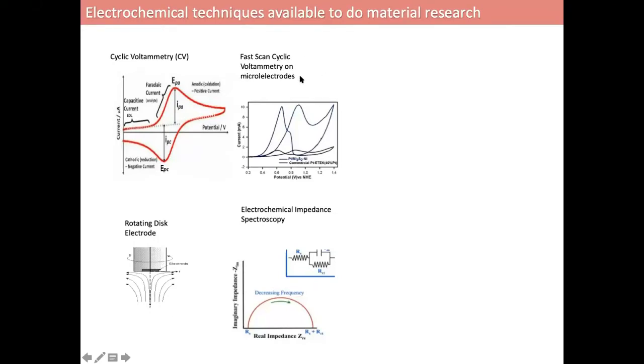It has to be done in a microelectrode. We're going to talk about microelectrodes very soon. Here in this case, we are scanning the potential at about 10,000 volts per second instead of 0.1 volt. So we can catch the fastest events, like sub-nanoseconds or microseconds, in charge transfer processes. This is possible for a physical chemist or electrochemist.